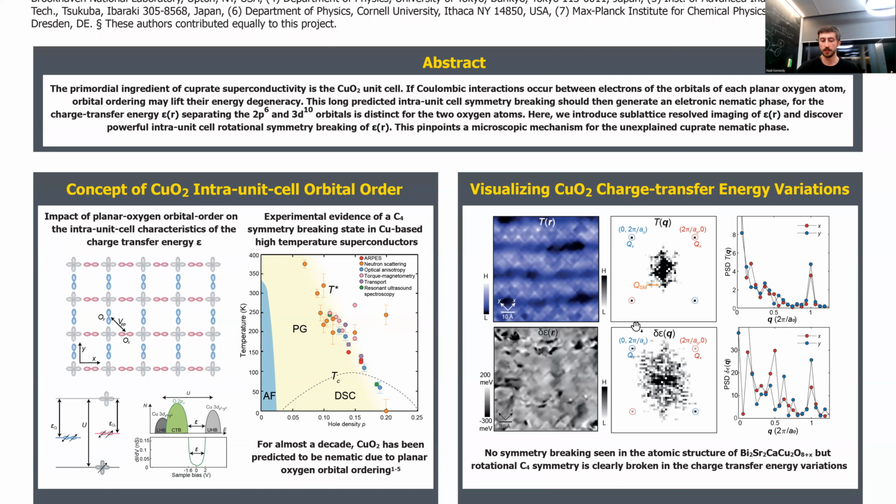So to investigate this effect, we used atomic resolution high voltage mapping from about minus 1.5 volts to plus 2 volts. And this was done on 17% hole-doped Bi2Sr2CaCu2O at 4 Kelvin with a junction resistance of approximately 85 gigaohms. So 85 gigaohms would be quite a high junction resistance, and this was done to preserve the sample surface during such high voltage mapping. So in the top row, I show the topography, and this is the topography of the bismuth oxide surface.